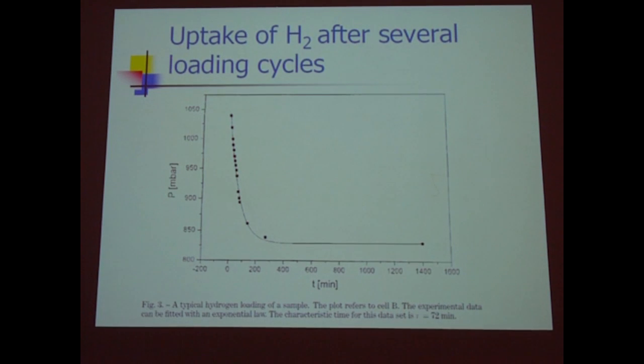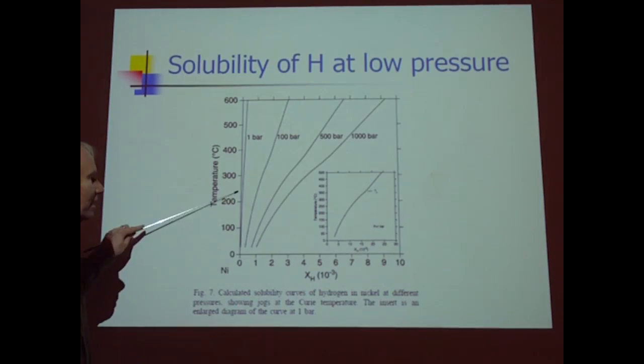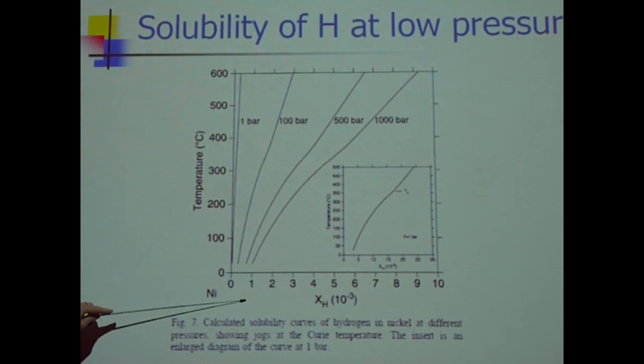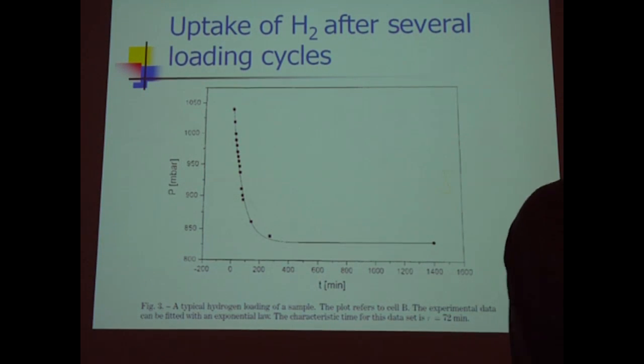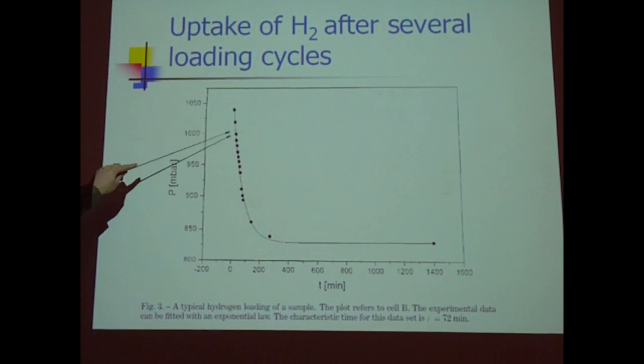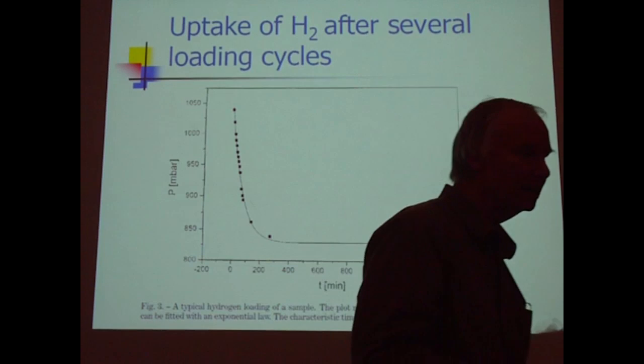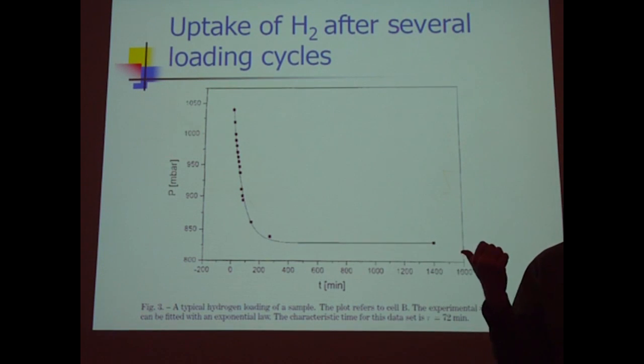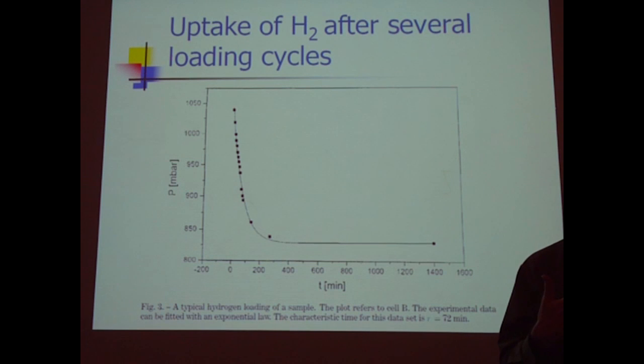Now if the hydrogen pressure is going down, well, where's it going? So for example, we had argued that the solubility of bulk nickel hydride is diddly squat. So we know that the hydrogen is not going into the bulk nickel. So where's it going? This is millibar, 1,000 millibar, 1 bar, roughly an atmosphere. So somewhere near an atmosphere, and the pressure drops down to sub-atmosphere. So I was looking at this, and when I saw this, this really caught my attention because it meant their sample's absorbing hydrogen. How does their sample absorb hydrogen? What makes it absorb hydrogen?